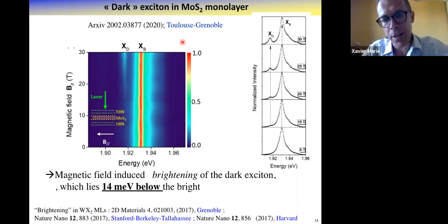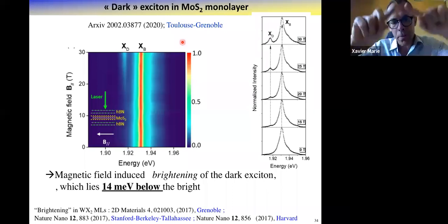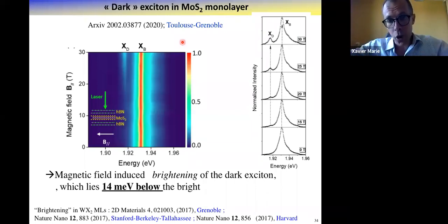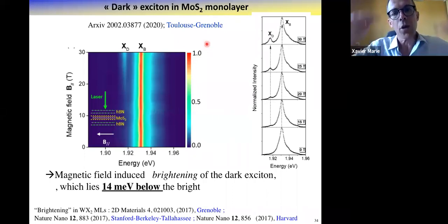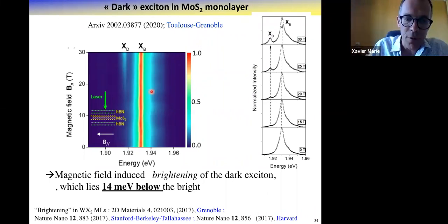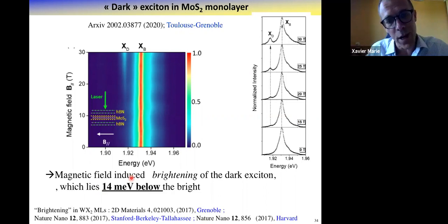The third ingredient is the fact that you build your exciton, bright and dark, with two different conduction bands, spin up and spin down, and those bands have slightly different masses. If they have slightly different masses, it will give slightly different binding energy, just a first order binding energy. So again, it will shift the dark exciton a little further down in MoS2. So our picture with this 14 millielectron volts is that indeed, it is very difficult to get a real measurement for the three contributions.